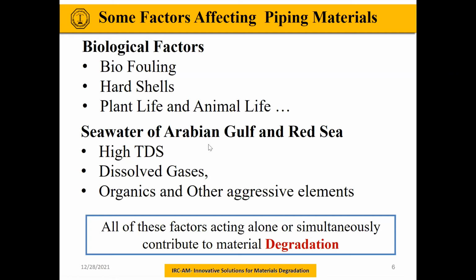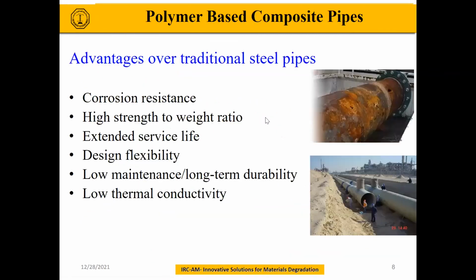The use of conventional materials in seawater of the Arabian Gulf and the Red Sea exposes them to high TDS, which is usually between 40,000 and 65,000 ppm, dissolved gases, organics, and other aggressive elements. All of these, acting alone or simultaneously, will contribute to material degradation. And that has been explained very well by our colleagues in terms of corrosion.